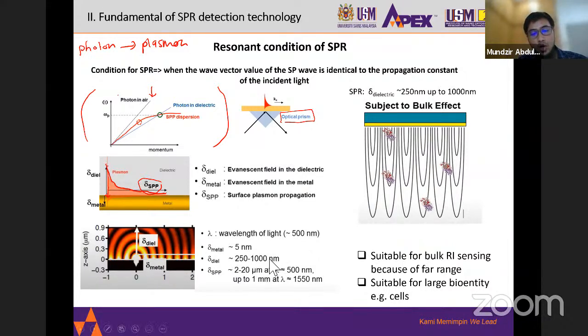But this is how we probe into the dielectric, right? And the propagation of the surface plasmon polariton can go up to 1 millimeter. The SPP wave that I showed you just now can propagate up to 1 millimeter at a certain wavelength and condition. All right. So this is the resonant condition of SPR or bulk SPR. We know it's bulk SPR because we use a thin film of metal, not nanoparticles, so this is called bulk surface plasmon resonance.